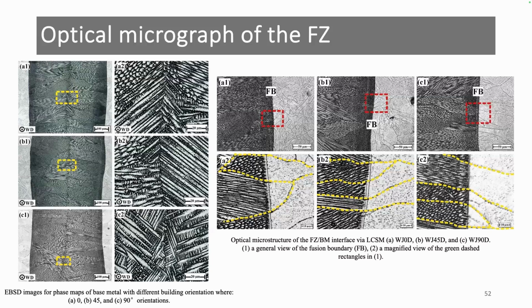We performed heat treatment at 1000 degrees Celsius for 60 minutes to relieve some thermal stresses. However, after the process of laser welding, we find that the base metal showed the cellular structure again. And when we zoom in on this area at the interface between the fusion zone and base metal, we will find that the main grain is also extended between the base metal and the fusion zone of the laser welded joint, and the same also for 45 and 90. So it means that the laser welding does not have an extreme effect on the orientation of the main grain boundaries in the base metal.